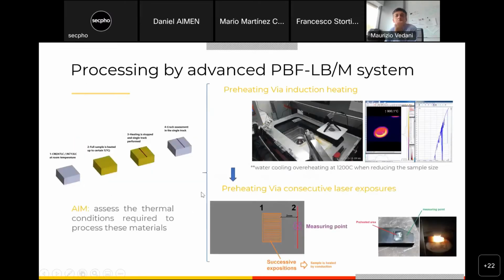Mauricio, if you can skip to the next slides. So regarding the first test, the study of these thermal cycles required in the process of these alloys, we followed, as you can see, two different approaches with the same purpose, which is to heat up a solid block that you can see on the left side. This block is made of these two alloys, the CM247 and Inconel 713 low carbon, and we heat up these blocks up to a certain temperature. And when this target temperature is reached, we stop the heating source and we perform a single track on the part. In this way, we are able to modify how the melt pool is solidified, and therefore we can manage the cooling rates during the process.